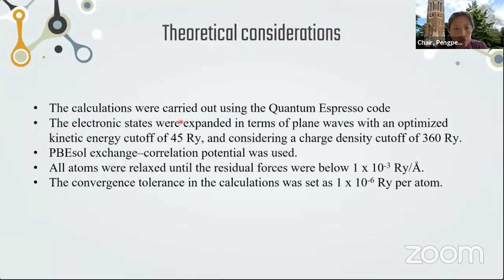The calculations were carried out using the Quantum ESPRESSO code. Electronic states were expanded in terms of plane waves with an optimized kinetic energy cutoff of 45 Ry, and considering a charge density cutoff of 360 Ry. The PBEsol exchange-correlation potential was used. All atoms were relaxed until the residual forces were below 1 × 10⁻³ Ry/angstrom. The convergence tolerance in the calculation was set as 1 × 10⁻⁶ Ry per atom.